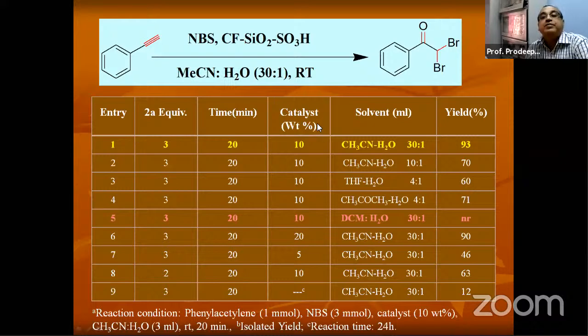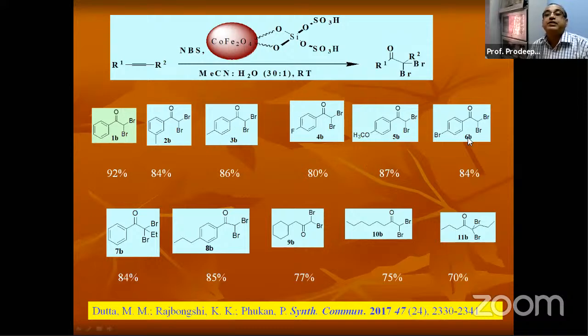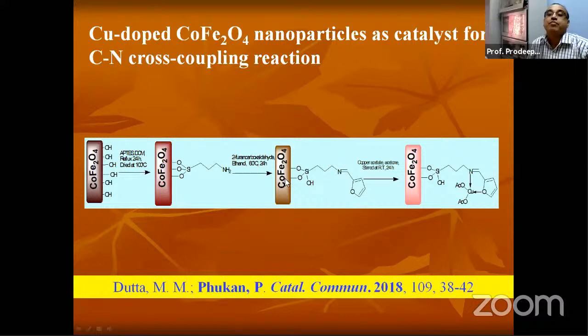And so we have done many permutations and combinations. We found that acetonitrile water 30:1 ratio is the best solvent for this kind of transformation. Yields are 93%. It's very high after 20 minutes. So these are different molecules that we have synthesized.